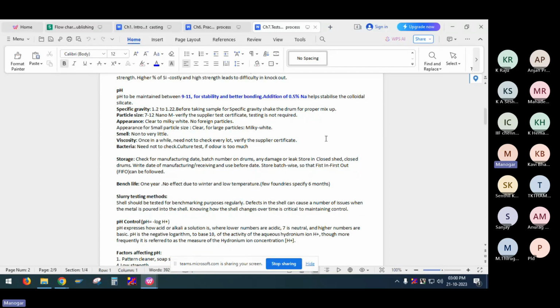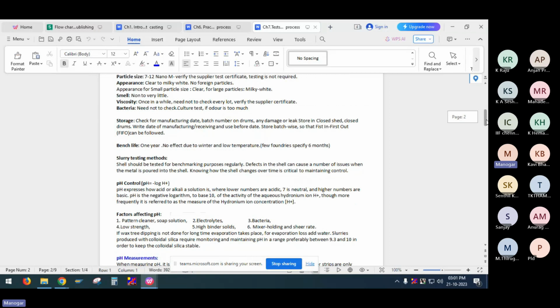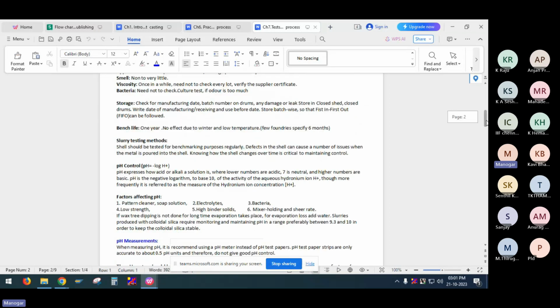The appearance should be clear, milky white, no foreign particles. Smell, there should not be any smell. Viscosity should be checked once in a while, or you can base it on the supplier certificate. Storage should be by date and batch number, and a first in, first out system should be followed. Shelf life for binder is 1 year, but some foundries specify 6 months. They don't want to store for more time due to their practical experience.